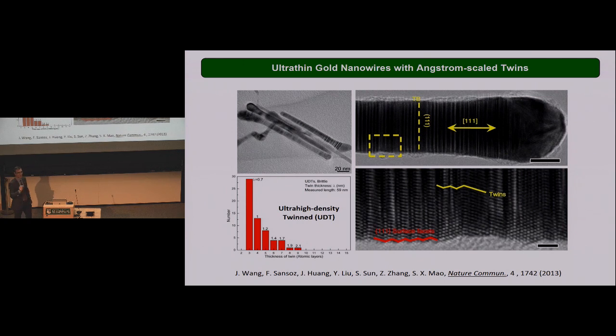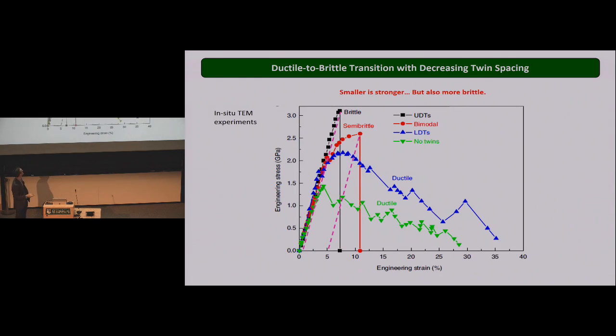The average twin spacing is just 7 angstrom. It's the minimum limit you can have between two twin boundaries. That's how stable and perfect they are at this scale. And so we repeated the same experiment. First, let me show you the difference in mechanical behavior. The green line represents a single gold wire that does not contain any twin, and it's very ductile. It's a stress and strain curve. You have a strength here and very ductile.